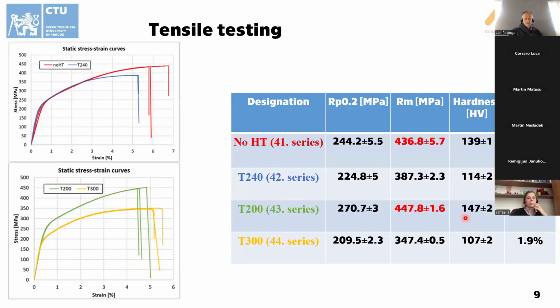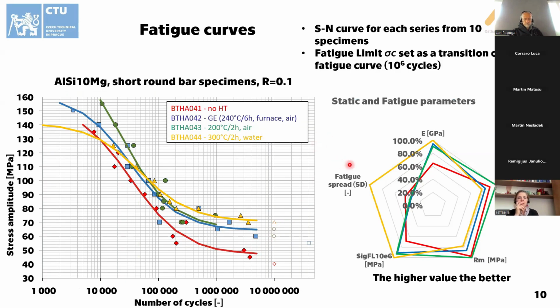Regarding the tensile test, this is only to mention the ultimate tensile strength, as it's further used for the fatigue limit estimation. What I would like to mention here is that the non-heat treated variant and the T200 have high ultimate tensile strength, and by increasing the temperature from 240 to 300, you are lowering the tensile properties of this particular aluminum alloy and lowering the hardness. This particular temperature, close to 300, dissolves or decomposes the silicon networking that acts like the brittle material, and lowers the ultimate tensile strength and hardness as well. But this can well transcribe to the fatigue life, as we can see here, because here are the results.